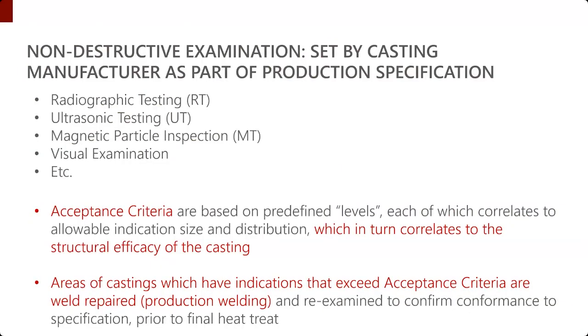And then NDT. So there's a suite of non-destructive testing. Some of these are in 1090 Part 2 actually described. A qualified casting manufacturer might even want to exceed the expectations of 1090-2 or an ASTM equivalent. And so it's important that in that production specification, the casting supplier has provided not only the suite of tests, but the frequency as well as the acceptance criteria using these standards that are relevant to the authority having jurisdiction.